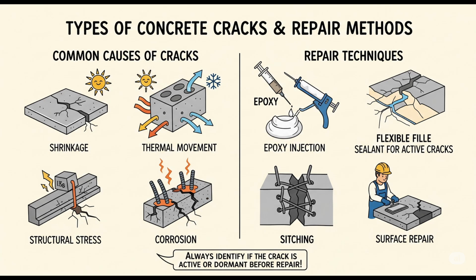Do top and bottom surface cracks mean different things? They often do. If you see cracks on the bottom surface of a slab, especially if they run in one or two directions and are accompanied by rust spots and maybe some concrete spalling, that's a pretty clear sign of rebar corrosion. Water has gotten in from below or maybe through the slab.